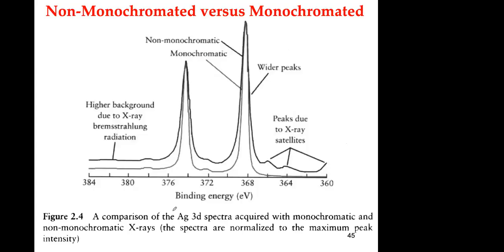Here is a comparison between a non-monochromated and a monochromated source. The non-monochromated is the wider one, with wider peaks. It also has some satellite peaks, as you can see here: that's one, two, and three. This is a spectrum of the 3d spectra.